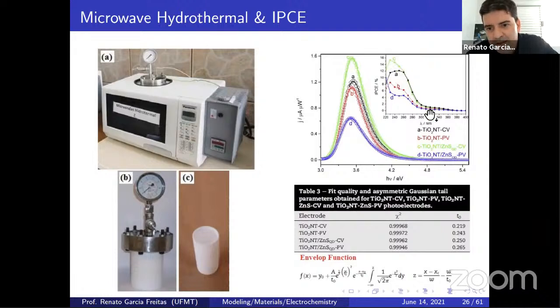Take a look here at C. We have the quantum dots, constant voltage higher, 16, than pulsed voltage, like down there, that one. For without quantum dots as well, we have the A, constant voltage, increased compared to that one, pulsed voltage, isn't it? And we fitted this value using an envelope function like this one. This envelope function was proposed by the group of Professor Alan Heeger, when they used to study conducting polymers, because as we see, the Gaussian function is not symmetric, isn't it? We have the asymmetry of this envelope function.